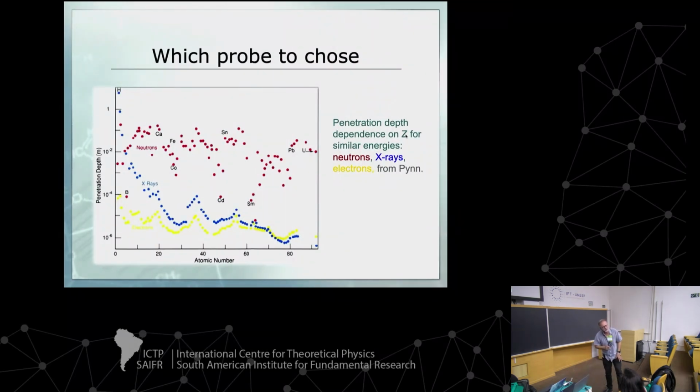It has no problem with the interfaces. But you mentioned the other techniques have problems with the interfaces. With neutrons, there are fewer problems because you can choose the material. There are lots of materials that are transparent, or where you know where the peaks are, so you can subtract. So you do the measurement of the cell in vacuum, and you have the peaks. You choose cells that have diffraction peaks away from the area you want to explore, and then you remove it. So it's much easier to handle than other things.